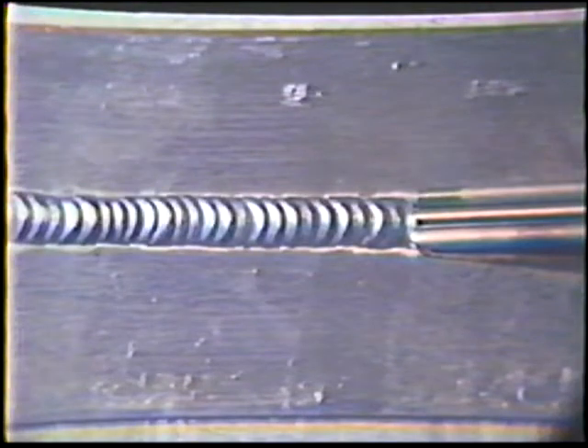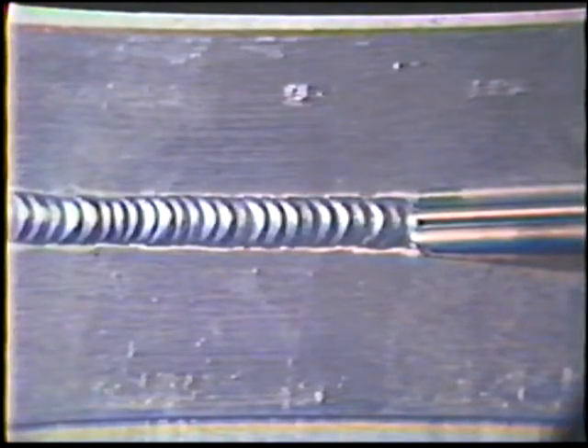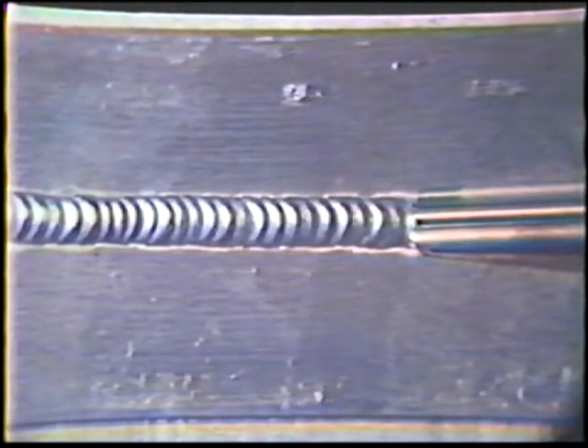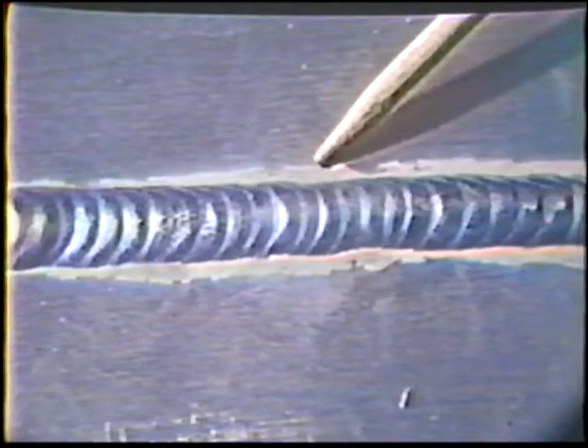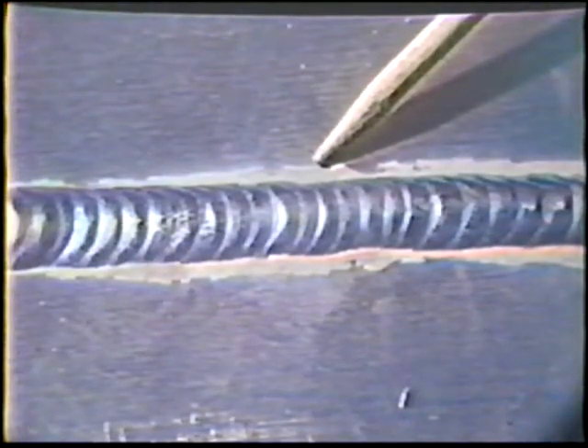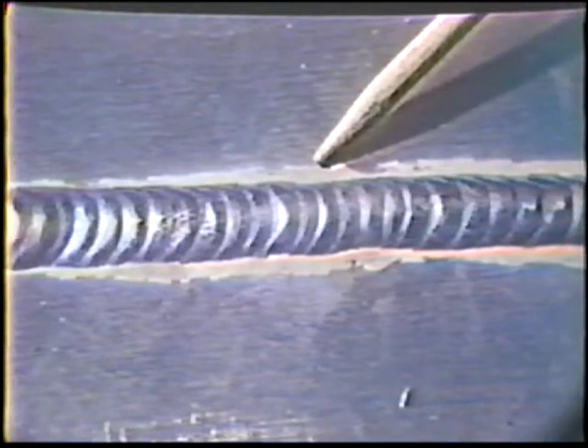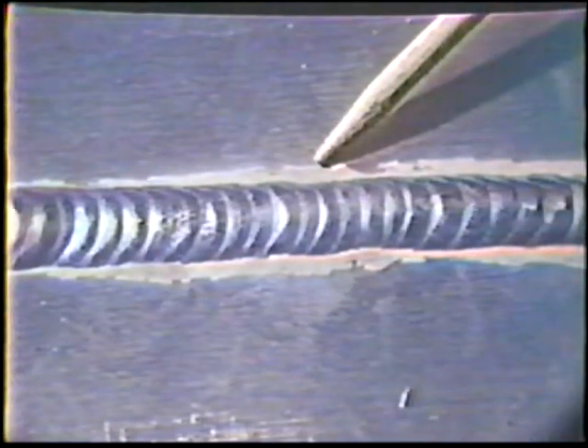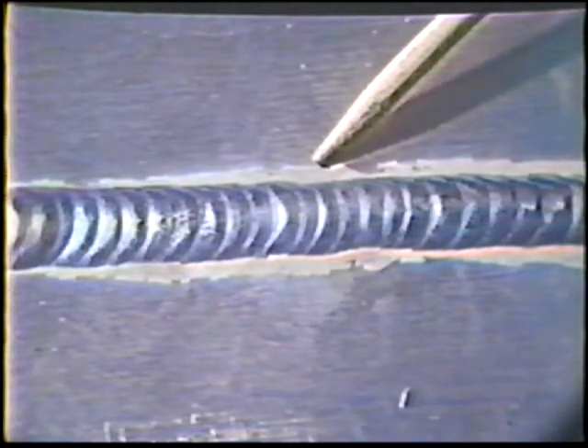The finished weld face should be evenly rippled, slightly convex, and 2.5 to 3 electrode diameters wide. Good cleaning should be indicated by a white line at the bead edges. This is actually the breaking up of the oxide coating on aluminum. Inspect the bead and then continue practice.